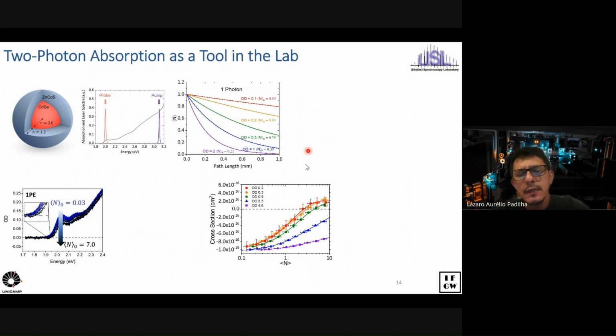Conversely, by the way, here is an example. When you change the optical density from 0.2 to nearly 5, you see that you get optical gain for the small optical density, because for small optical density, your excitation through the sample is nearly constant. On the other hand, when you go to high optical density, you will never have optical gain, because you're always going to deplete more of your beam than you should.